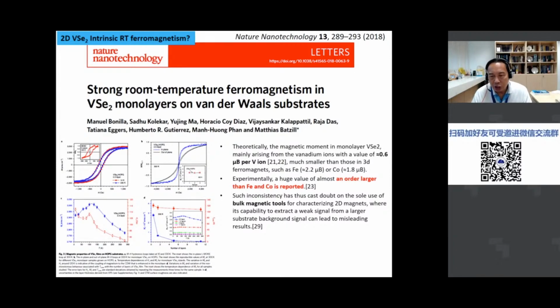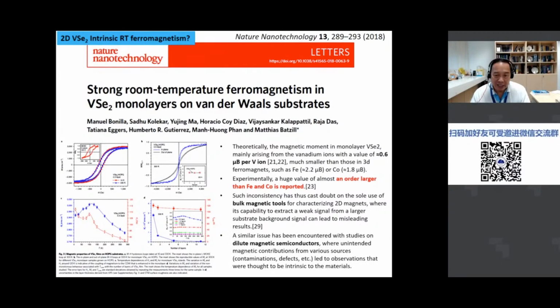And this is the challenge whenever you're trying to measure magnetism on very thin 2D layers, where you're trying to get weak signals from a large background. So we are not saying these results are wrong, but we are saying that, similar to the field of dilute magnetic semiconductors, you can get unintended magnetic contributions from various sources. So it could be that there are contaminations, or it could be that there are defects on the samples that lead to these observations. And that's why in this case, the value of the magnetic moment is so much larger than that predicted. So KIV, this Nature Nanotech paper.